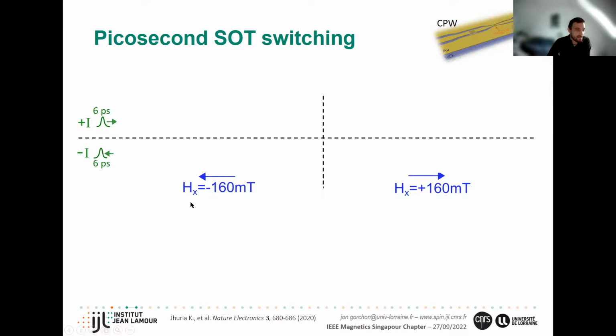And we tried to do the same experiment with single current pulses. So we're looking with the MOKE microscope now. It all looks gray because we're doing differential imaging. So you'll see this magnetic region here. It will switch colors when we switch the magnetization. So if we put a pulse with this polarity, say I would call it positive current and negative in-plane field, after a single shot, you can see that the magnetization switches.